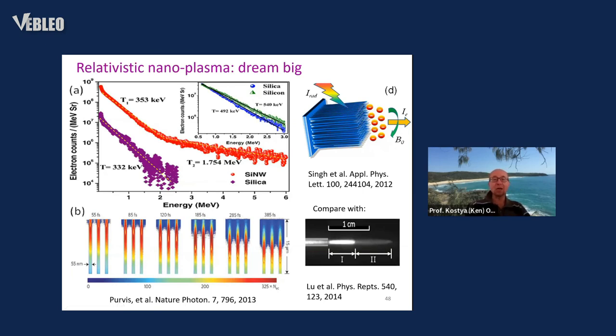And what is really interesting is, remember, at the beginning of the talk, I said that plasmas could be very, very fast. And this nanoplasma is extremely fast because, as you can see, this is the dynamics of the development of nanoplasmas, which takes just a couple of hundred femtoseconds. Femtosecond range, how the plasma evolves over such very short periods of time, which is much faster than the formation of, for example, microplasmas that we generate using atmospheric pressure plasma jets and other systems that we have at atmospheric pressure conditions.